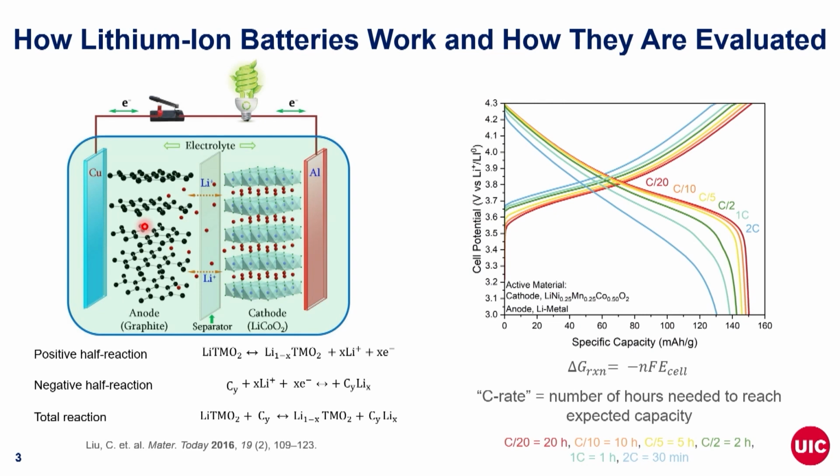which is basically a salt electrolyte that is ionically conductive but not electronically conductive. This allows for lithium ions to move and then flow through this ionically permeable membrane and then intercalate into our cathode structure opposite of the anode. Since the electrolyte is ionically conductive and electronically insulating, this forces the electrons to move through an outside circuit through this copper current collector, and then move through your device to power the device, and then recombine with our lithium ions in the solid structure through the aluminum current collector at the cathode.